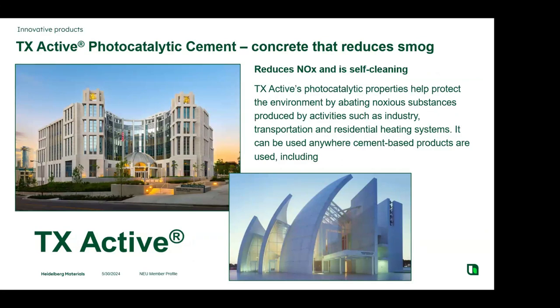The amazing thing about this cement is they sometimes call it a smog eating cement, because it will actually mitigate NOx. It will pull NOx right out of the air through a photocatalytic reaction on the surface of the concrete. And through that process, it has what they call the Lotus effect. So not only is it cleaning the air and scrubbing the air from smog generating NOx, but it's also self-cleaning, where the concrete itself actually self removes the soot and soiling that can accompany the surface of concrete.